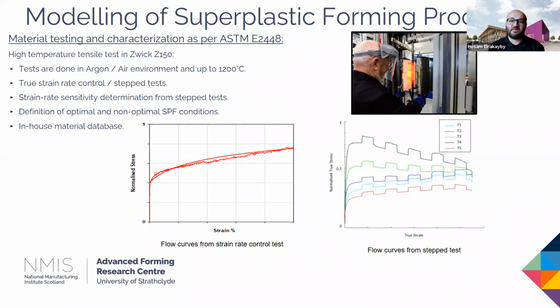We do high temperature tensile tests on our Zwick testing equipment. Tests can be done in argon environment and up to 1200 degrees Celsius. We need the material properties from two types of tests, the step jump test and the normal hot tensile test, to have the flow curves at different control true strain rates at required temperature. As a result of the various tests we completed for different alloys, we have a good expertise in testing different materials. Then once we characterize the material and based on the test result, we can define the optimal SPF conditions.